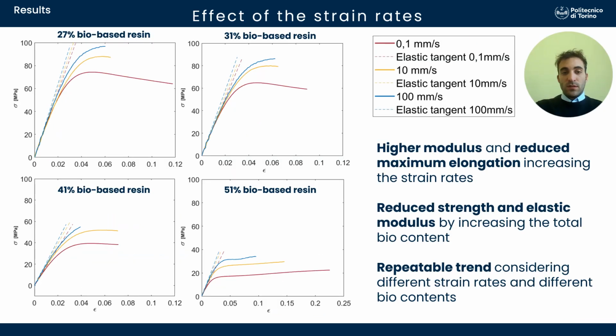Here I reported the same stress-strain curves for the 4 different tested materials, but with the aim to highlight the effect of the strain rates. In fact, by increasing the strain rate, we can see that we obtained a higher modulus and a reduced maximum elongation. Whereas by increasing the total bio content, we had a reduced strength and a reduced elastic modulus. Overall, we can see a repeatable trend considering different strain rates at different bio content.